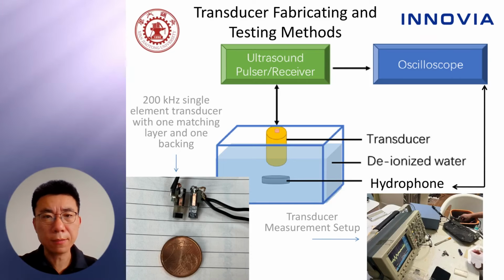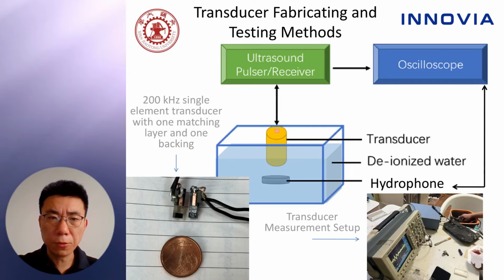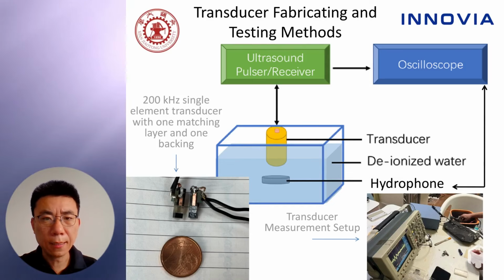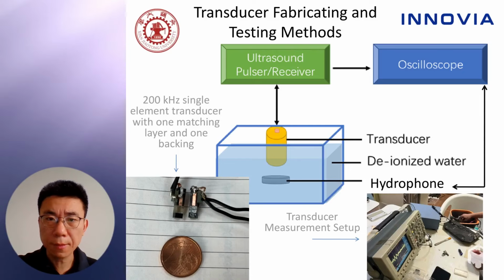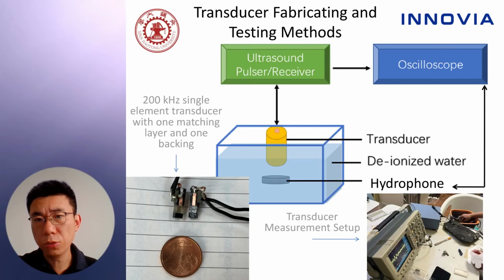Let's look at the transducer fabricating and testing methods. First of all, crystals of different poling conditions will be manufactured into single element transducers corresponding to 200 kilohertz with a typical application of breast cancer treatment. They have 1 matching layer and 1 backing. Those transducers, together with a hydrophone, we put under water in the water tank, 20 millimeters apart. The transducers would be connected to an Olympus ultrasound pulser receiver, which is then connected to an oscilloscope. The oscilloscope will generate the waveform that we needed for measurement of minus 6 dB bandwidth and sensitivity.